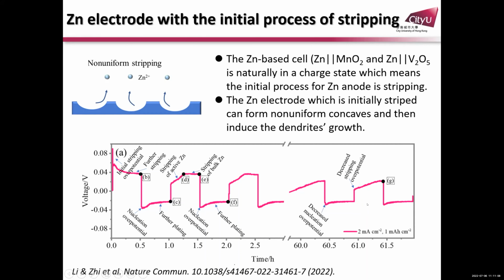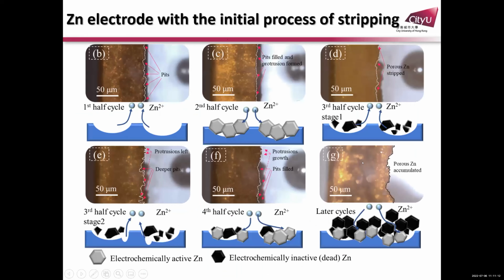Then after a certain time, you will have a decreased stripping overpotential. If you look into the details of the structure, starting from the first cycle, you have some pits. Originally, it's not totally smooth. If you go for stripping, then your surface gets much rougher, with some dead zinc growth on the surface. Then the surface will get a lot of porous zinc accumulation. The surface is getting rough.